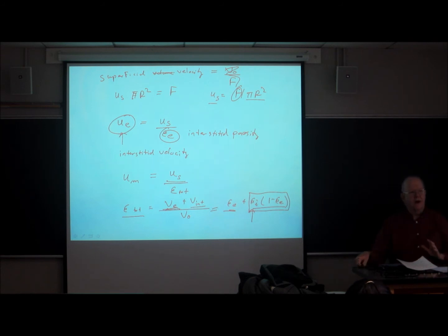In gas chromatography, because the pressures are not very high, they will sometimes use particles with very, very high internal porosities, maybe even 0.8. The pressure is so low that you're not going to break the particles. But if you try to do HPLC with a particle whose internal porosity is 0.8, the particles are just going to be crushed immediately.